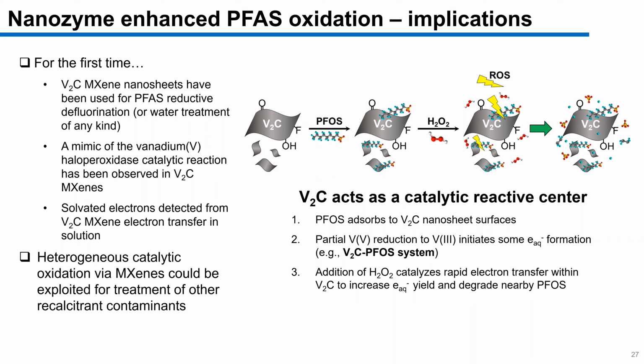So we're at low levels, and our hope is by shifting to this electrochemical application, we can eliminate any leaching of vanadium or exposure to vanadium by fixing the vanadium carbide onto the electrode surface. Okay.